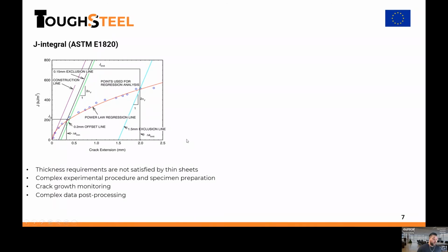Now, an important consideration here is that this standard procedure is intended to evaluate the plane strain fracture toughness of metallic sheets. So the thickness requirements described in this standard cannot be satisfied by thin sheets like the ones under consideration. We are talking about sheet thicknesses ranging from 1 to 3 millimeters in most cases, in the automotive sector.